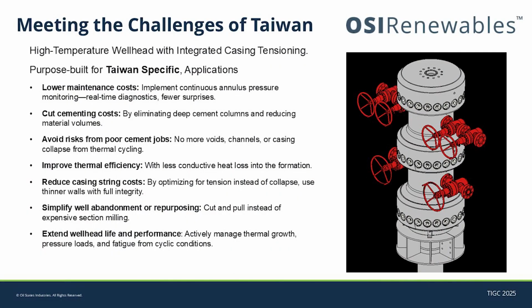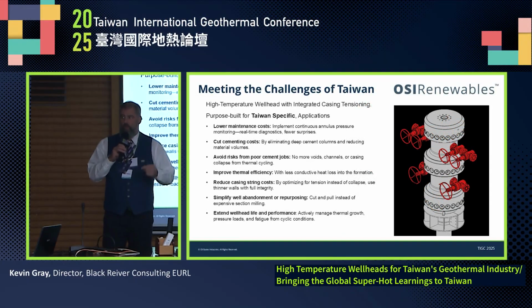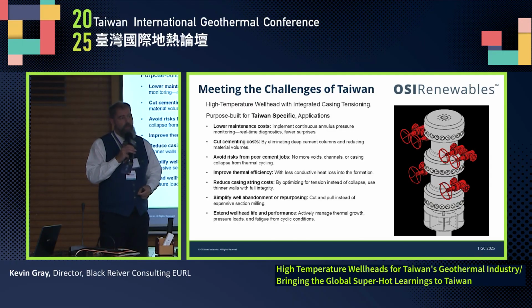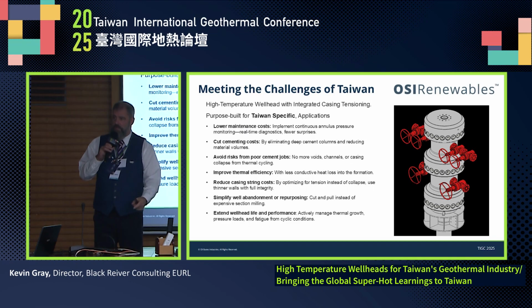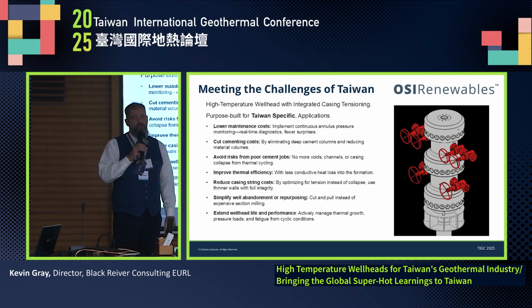So the idea behind this technology is that we cement conventional. How much retarder do you put in for the cement coming close to surface versus the cement down in the hot part of the well? If we don't put enough retarder in and we're pumping and cementing a hot well conventionally, and conventionally means the cement goes down inside the casing and comes up the annulus, what will happen if we don't have enough retarder in, is that the cement will start to set up